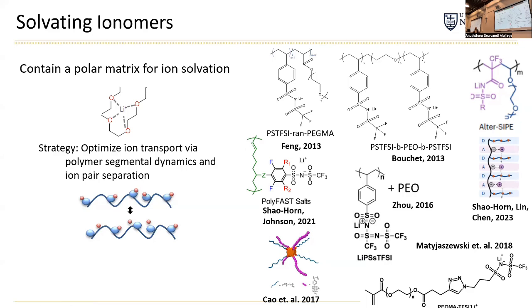And then once the lithium is solvated by the plastic, its ion transport, we more so understand this part. Once it's separated from the anion, the polymers move segmentally, so they wiggle back and forth. So with increased temperature, they wiggle faster. And in the presence of an electric field, the lithium will move between coordination sites as the polymers move. And so the rate at which the lithium moves in this type of environment is totally coupled to what we call polymer segmental dynamics, which is how fast the polymer is wiggling like this.